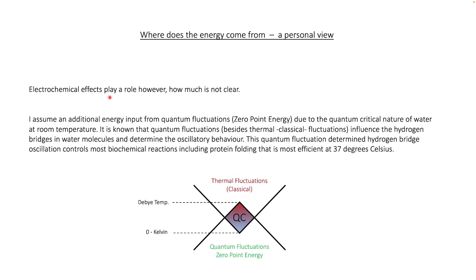However, 1 gram of aluminium produces about 3 ampere hours, and when putting the crystal cell on the load for about 1 year, I could calculate the current and therefore the amount of possible corroded aluminium, and I have measured a 10 times lower amount of corroded aluminium in comparison to the current generated. So there should be another source of current, and that fits together that the cell is a current source. And where does the energy come from?